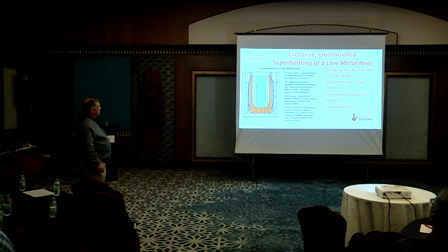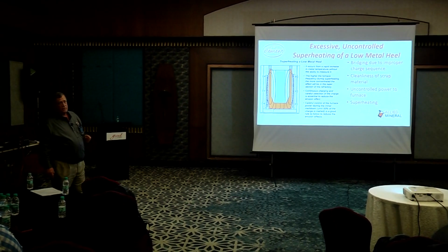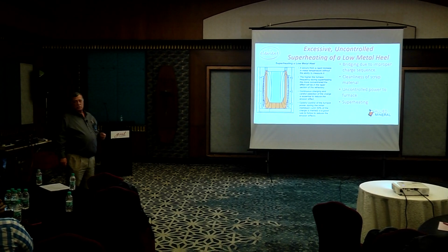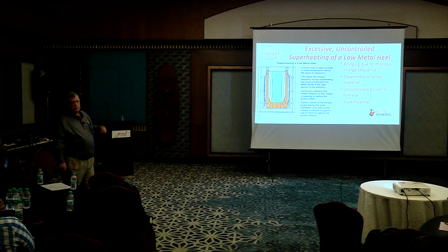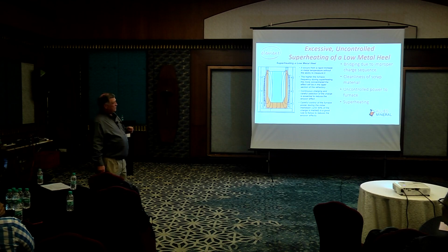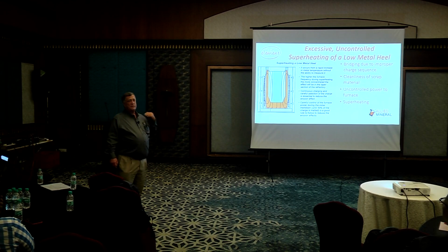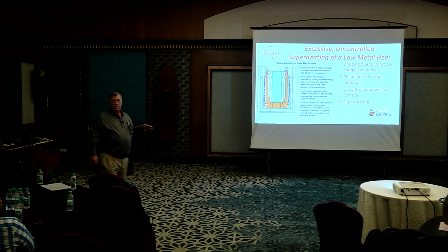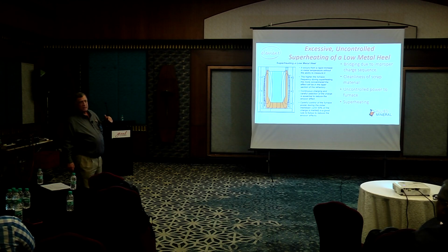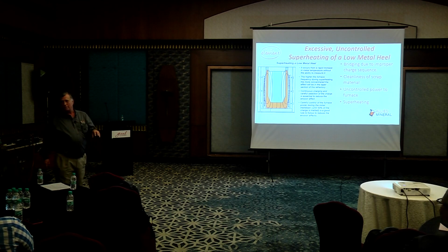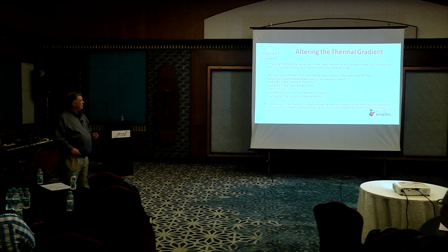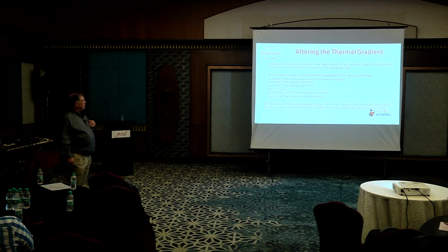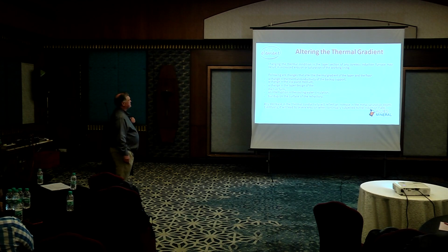Excessive uncontrolled superheating, we talked about that also. Freezing the furnace. Adding too fine a charge in the bottom of the furnace, too dirty a charge in the bottom of the furnace, where you're going to get superheating. And superheating is simply using too much power, or bridging, where you're using the normal power, but you're heating a much smaller volume of metal. So altering the thermal gradient, changing the thermal conditions of the taper section.